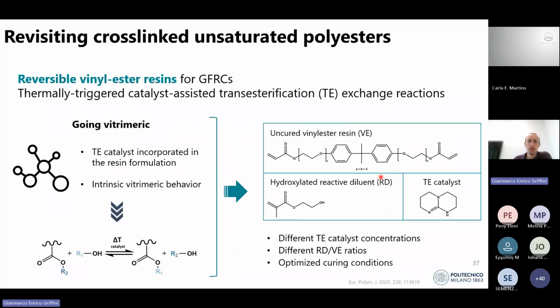material and going towards the use of vinyl ester resins that could be cross-linked with, again, a methacrylate, hydroxylated reactive diluent in order to provide, after cross-linking, the possibility of having again a three-dimensional reversible system based on the vitrimeric chemistry through transesterification reactions.